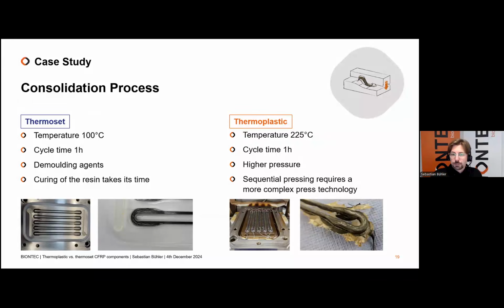In this case we have a steel mold, also for the thermoset route, and therefore we always have to cool down the process, then do the preforming, and then heat up again and do the consolidation. And as some of you are perhaps familiar with, if you consolidate a commingled yarn, you can't just close the mold. You have a sequential pressing, because you have to get rid of the voids and the air in the preform, and this has to go step by step.